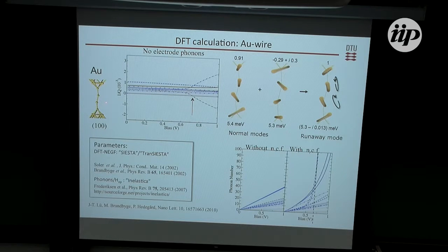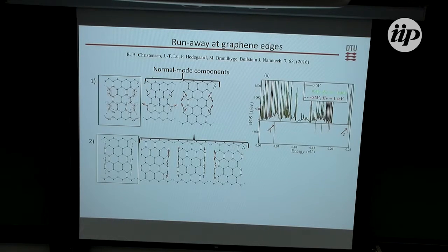And I should say we are not neglecting the phonon reservoir, the damping to this, which is very important in this case. But anyways, it goes to say that this is not necessarily a very, very small effect. We have recently looked at the effect where we include all the coupling to the phonon reservoirs and so on, where we look at this, again, this kind of nano ribbon. And the nice thing about it is that if you strip away some of the hydrogen passivation, then you get some localized vibration at the edge here.